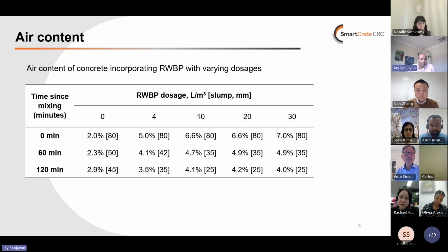Here you can see the amount of air that goes into the concrete when we add water-based paint. And that is mainly the reason the slump goes up, because we're introducing air into the system. So this is the amount of air after we cast into the concrete. So the first one, you can see there's a slight increase in the air in the concrete if we cast later, mainly because the slump is decreasing, so they introduce more air.